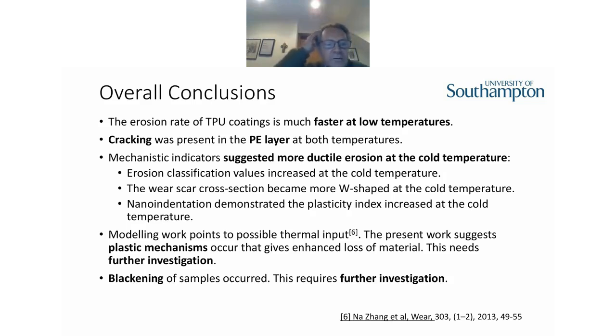So just some conclusions then. The erosion rates definitely are higher with lower temperatures for the polyurethane. There's cracking at the PE layer, which would need to be sorted out going forward, because that will take the service life of the top coats down. It looks like it's more ductile at low temperatures, which is a surprise. You've got nanoindentation confirming that plasticity index increased at lower temperatures.